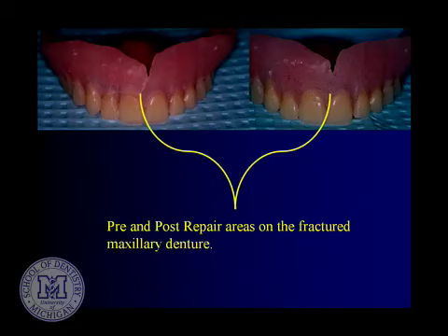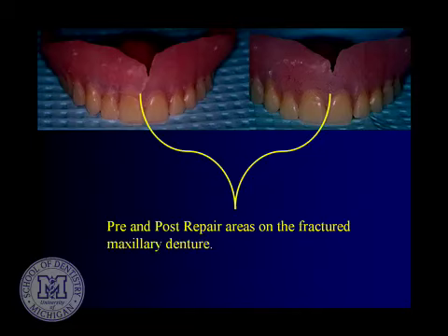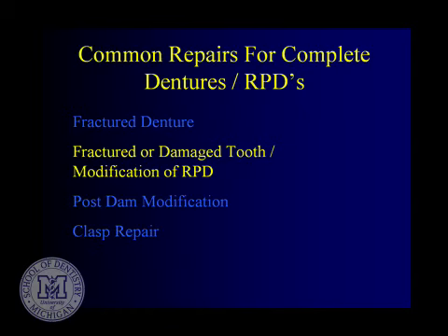What if we have a fractured or damaged tooth? If a patient's tooth just delaminated from the denture without breaking—they still have the intact tooth—take a medium skinny acrylic burr and lightly freshen the plastic in the divot the tooth left, slightly freshen the plastic on the lingual of the tooth. The tooth fits right back in the same spot; relieve a little from the lingual or palatal aspect, flow repair acrylic in, and it will seal very nicely.